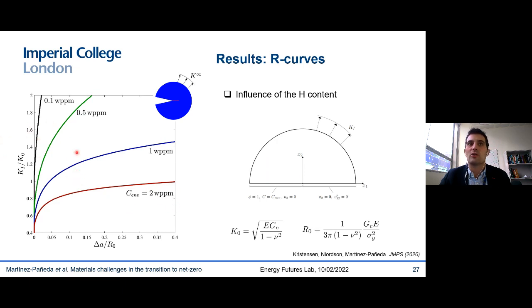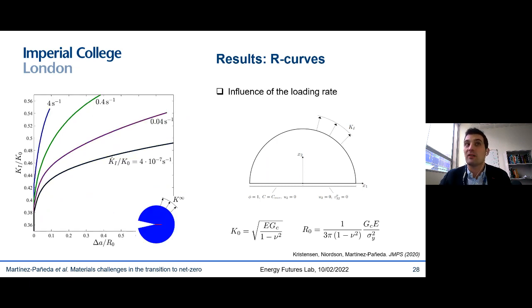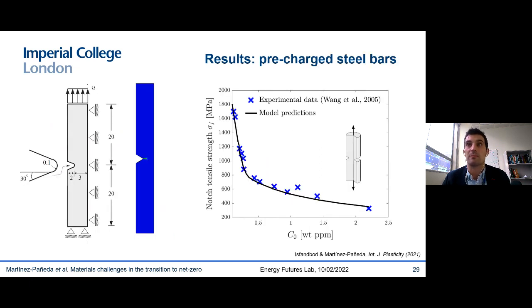As you increase the hydrogen content, the fracture resistance of your material goes down. And what you see here is the influence of the loading rate. If you load very fast, then there's no time for the hydrogen to accumulate in the fractured region. So you again have higher resistance to crack propagation. If you load very slowly, on the other hand, then there's enough time for hydrogen to accumulate there, and then fracture becomes easier.